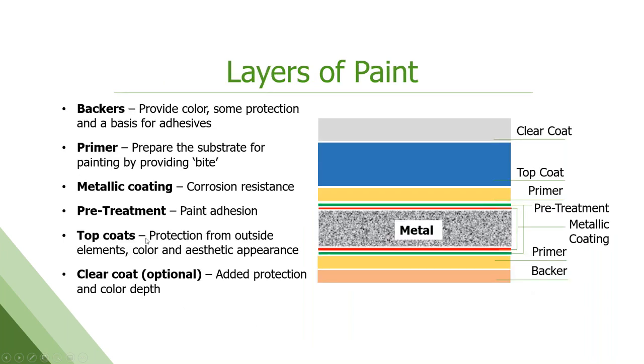Layers of paint. We don't do just one layer of paint, for a lot of reasons. So this is a cross-section of what the strip would look like. You've got your coated steel in the middle here. You're going to have a very thin layer of pretreatment that preps the surface for good adhesion to the paint. You're going to put a primer on. Our primers provide a lot of corrosion resistance. They also provide the bite, or the surface, for the top coat to adhere and link to when you apply it. Then you have your top coat.